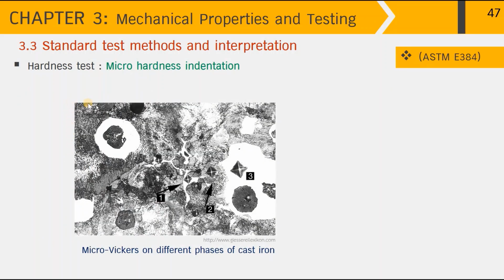So I'm giving you an example here. You might not have seen this picture before. It is the microstructure of cast iron showing different phases when we look under the optical microscope. Giving you a little more detail here: the phase that is looking spherical here is the graphite. Surrounding it is the ferrite, which is softer than the matrix lying over here. And you can see the laminar structure of the pearlite. Delineated along the arrow here is the carbide, which is the hardest phase.